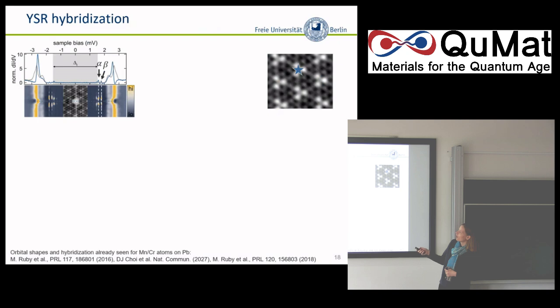So here you see the topography always in an inset, in an energy range where nothing happens in the spectra. So therefore I can nicely overlay it. But now essentially what we do is, the blue spectrum has been recorded just right on top of the atom. But if we take spectra that are across this line and plot them in a color scale, you already see that there's variation in the spectrum depending on the distance. So not necessarily on the very center do you see the largest intensity. For instance, here you wouldn't, but you see it slightly further away. These alpha and beta states that are labeled here get much more pronounced. You see here that there are other states also in the high energy part that you see in the color plot, maybe even more evidently.